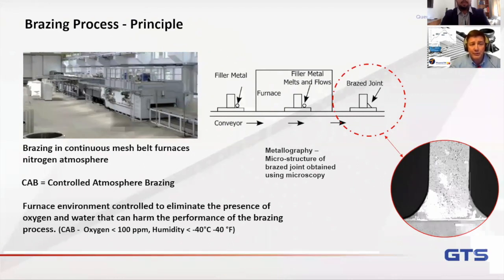We do, and that's what the majority of this presentation will be on: the monitoring of CAB processes, controlled atmosphere brazing, where you've got an environment inside the furnace which is being controlled to overcome the one pitfall of the aluminium brazing process, which is the formation of aluminium oxide. Because if you don't control the environment inside the furnace, the oxide layer forming on the substrate itself will prevent the alloy filler metal from flowing correctly into the joint, and you won't then get the good, secure fixing between the pipe and the fin, which could cause degradation or failure in the field.